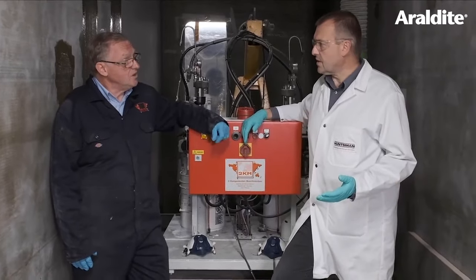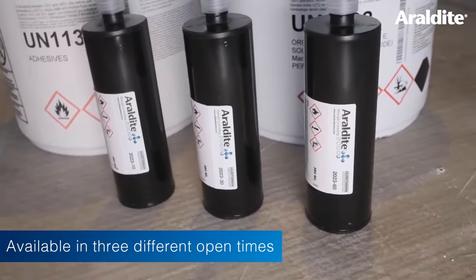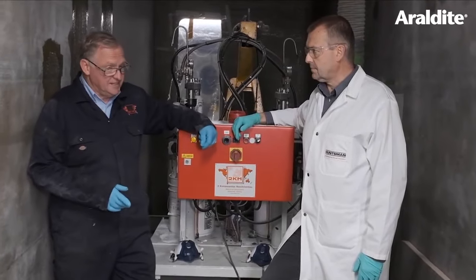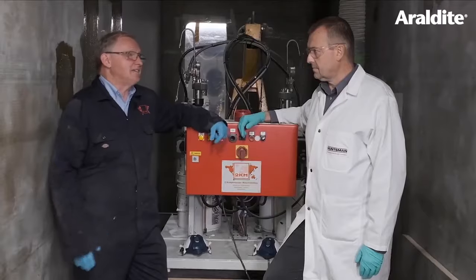So Araldite 2023 comes in three open times: 10 minutes, 30 minutes, and 60 minutes. Which open time do you use on this machine? At the moment we're using 10 minutes, which allows us to apply the adhesive and take the guides and clamps off within 30 minutes of application, and we can then move to the next area of bonding.